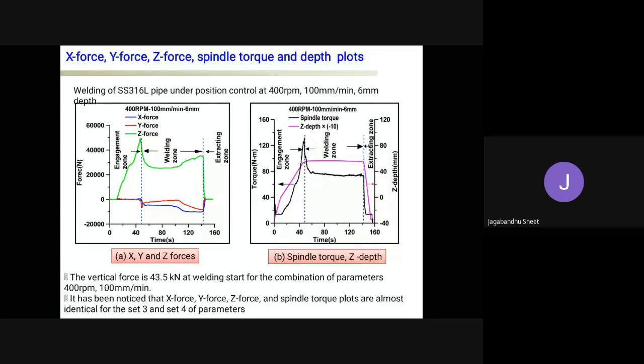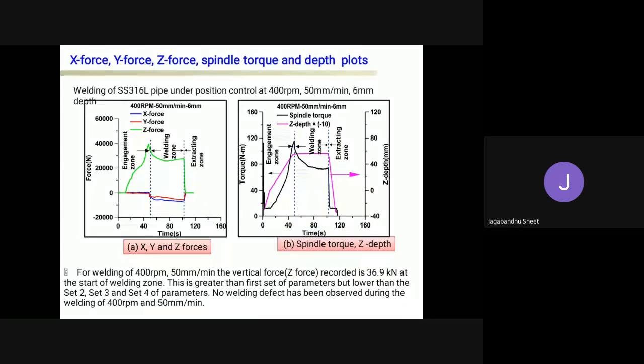This is the fifth set of process parameters. The process parameters were 400 rpm, 50 millimeter per minute, and 6 millimeter depth. In this set of process parameters, the vertical force is recorded at 36.9 kilonewton at the start of the welding zone, and there has also not been any defect shown.